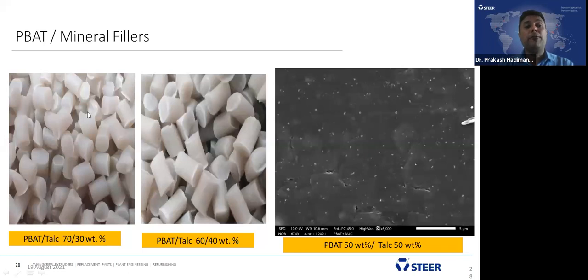Now, we are going to PBAT and the mineral filler. Mineral filler, we are talking about one is talc and the other calcium carbonate. Now, in this slide, we are discussing the talc addition. When you add talc 30% and 40%, it shows an increase in the mechanical property. The surface was smooth and there is a homogeneous mixing for the PBAT and the talc.